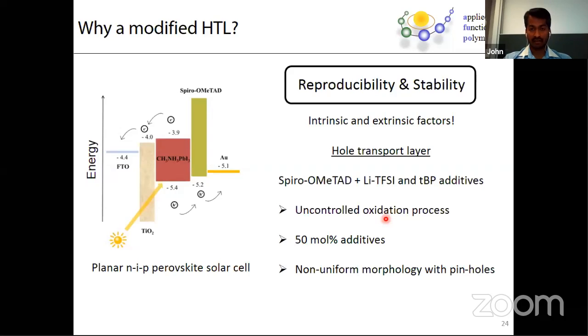There could be intrinsic and extrinsic factors, and one of the major contributing factors is actually the hole transport material, because in these regular devices, spiro-OMeTAD is still doped with lithium TFSI, another inorganic salt. You need to add this salt to spiro-OMeTAD to p-dope it, so that you can improve the conductivity of the system. The problem is the amount of lithium TFSI added to the system is more than 50 mole percentage, basically. So you have a 1:1 ratio of lithium TFSI and spiro-OMeTAD. So more dopant than the spiro as such.